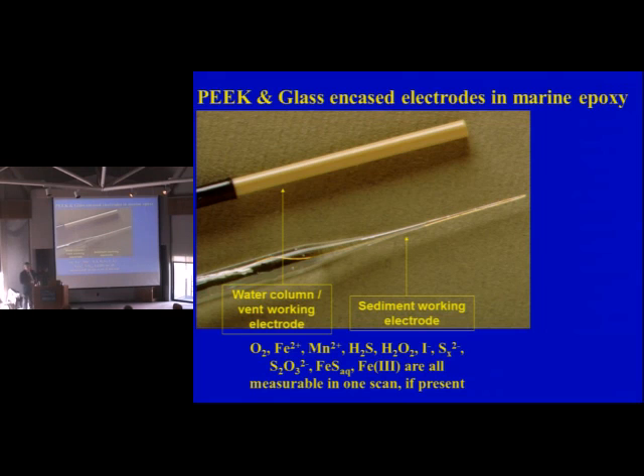But we can measure every one of these particular species or determine their absence, which is just as critical. So if something's non-detectable at a particular detection limit, that's useful. In addition to this, we can even measure reasonable levels in the sediments, and I showed in Jim Bishop's class yesterday that we could actually measure lead in salt marsh soils that were contaminated at about 5 micromolar level or so. So we could even measure zinc, cadmium, lead, and copper, potentially.